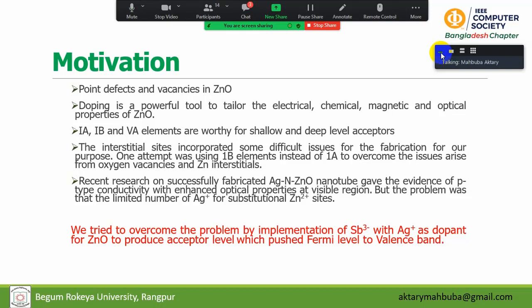The interstitial site incorporates some difficult issues for fabrication for our purpose. One attempt was using a 1B element instead of 1A to overcome the issues arising from oxygen vacancies and zinc interstitials. Recent research on successfully fabricated silver nitrogen zinc oxide nanotube gave evidence of p-type conductivity with enhanced optical properties in the visible region. But the problem was the limited number of silver atoms for substitutional zinc sites.